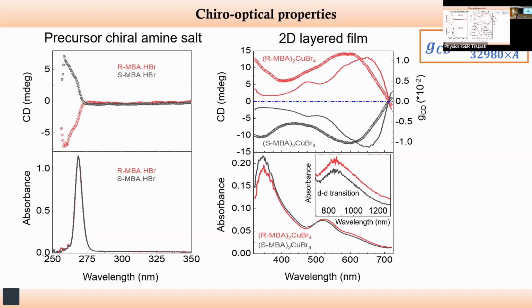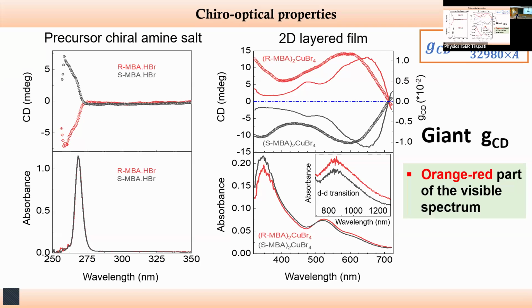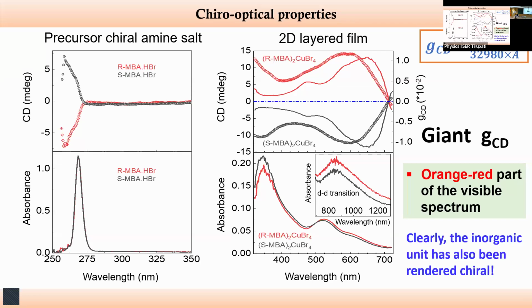You see huge chirality. This is a CD signal. Huge chirality transferred. These are states coming from bromide. So copper bromide becomes hugely chiral, which it normally is not. And so the chirality could be transferred from here to there. And in fact, it turns out that it is the record high chirality in this orange red part of the spectrum in this class of compounds so far. This still holds that record.